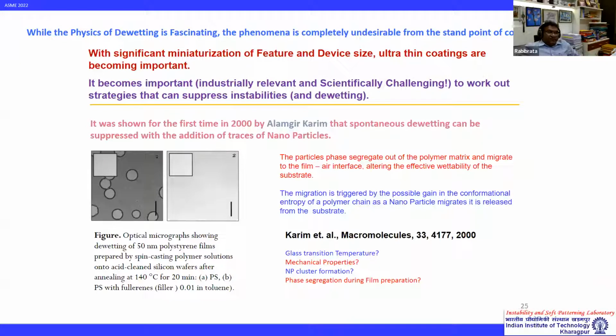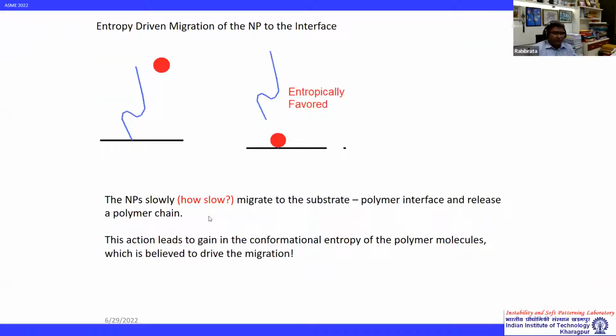The first paper demonstrated this by adding some fullerene nanoparticles, and they could show that a film which would otherwise become unstable, with the addition of fullerene nanoparticles in trace amount, does not dewet anymore. There is a lot of controversy and ongoing research on what exactly happens. Finally, people concluded, and we also did some work, that probably these nanoparticles eventually migrate through the polymer matrix to the film substrate interface, and they get anchored there like this.